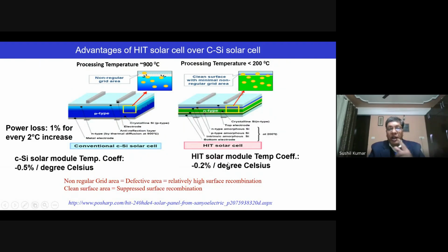In the previous talk, I entered 10 minutes before and I was listening that one question was asked about temperature. Of course, under high temperature, the performance of a solar cell deteriorates. But this is the beauty of amorphous silicon. One has to measure the temperature coefficient parameter. For crystalline silicon, it is much, much higher, like 0.5 percent per degree Celsius. Here it is only 0.2. So degradation is less. In places like Rajasthan, this will work much better compared to crystalline silicon. And the power loss is 1% for every 2 degrees Celsius increase.